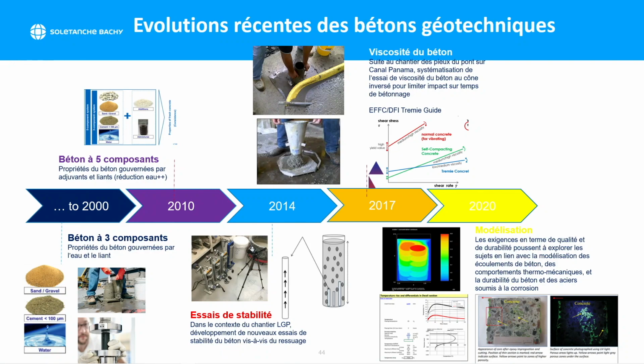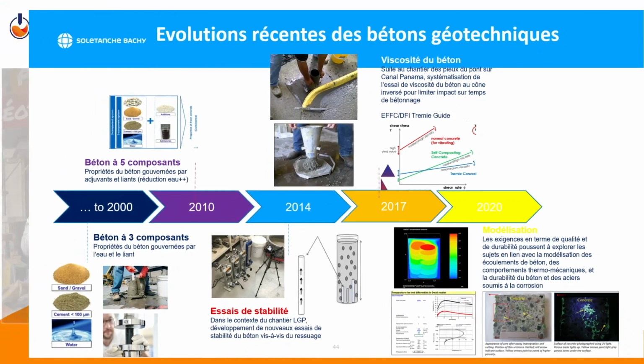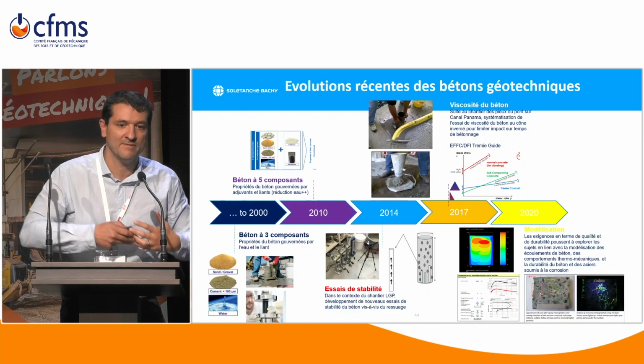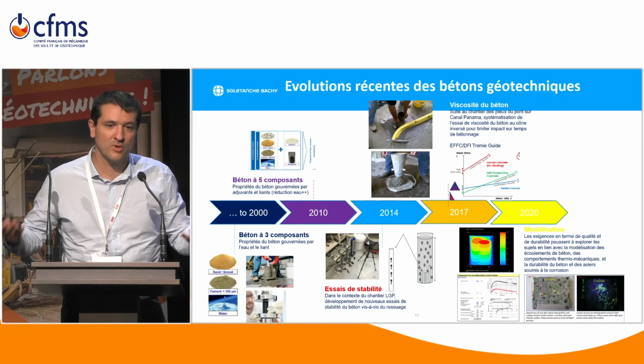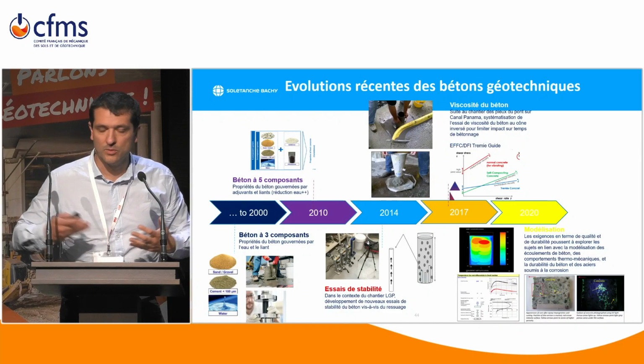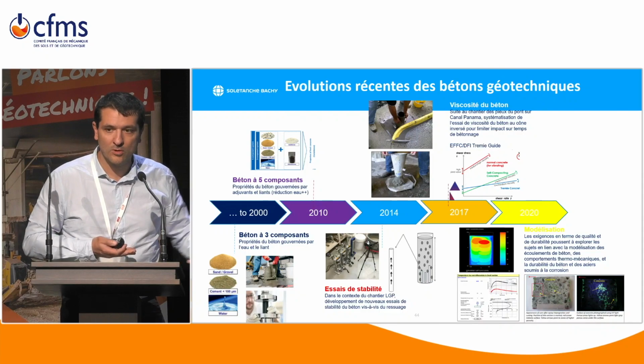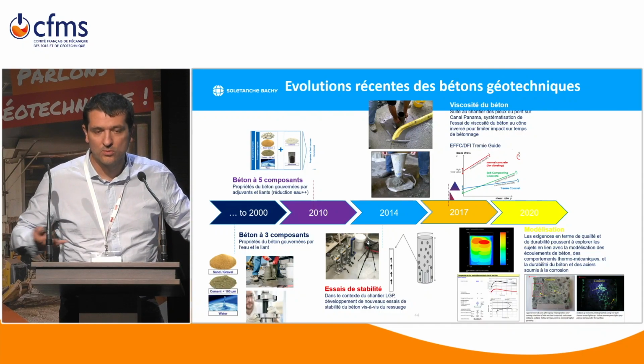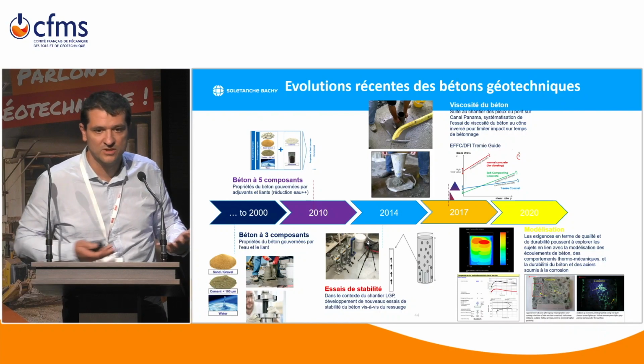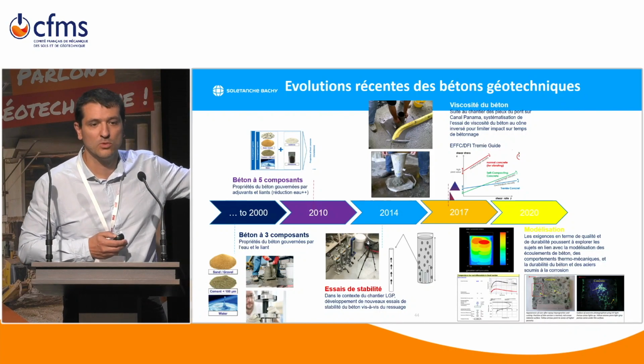And typically, for example, for the pours that were lasting 20 hours in London for deep shafts, we never use a concrete that has 20 hours of workability retention, because it would have led to a huge problem in terms of setting time. But we were able to pour a 20-hour pour with 8-hour workability retention concrete. And we demonstrated that it was working through modeling.